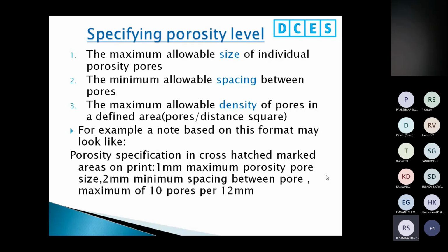For example, a note based on this format may look like: porosity specification in cross-hatched marked area on print. Print means drawing. 1 mm maximum porosity, pore size 2 mm minimum spacing between pores, maximum of 10 pores per 12 mm. So this is one methodology to specify the porosity in the casting.